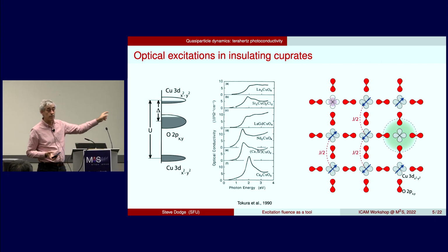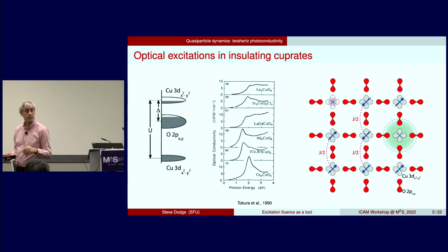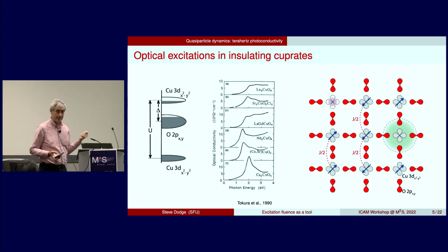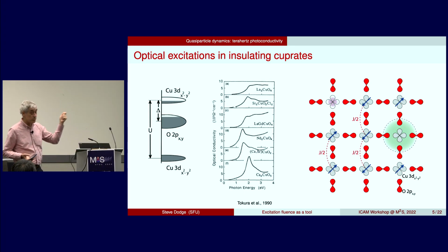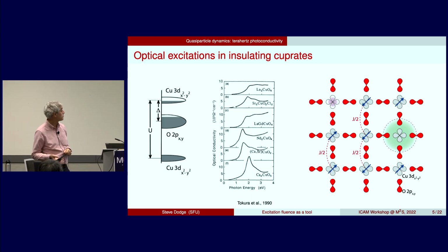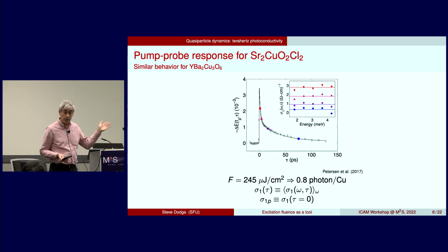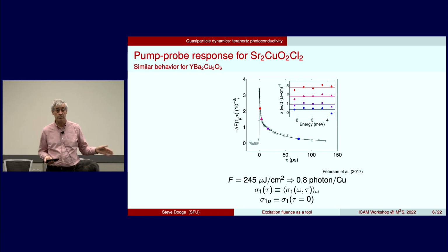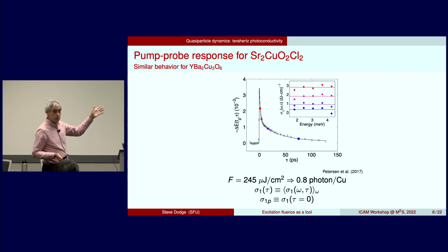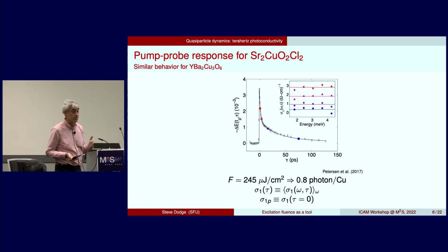But of course, as it does so, it leaves misaligned spins. So it's not immediately obvious that that is a free carrier, because there's an energy that it loses as it moves away from what I'll call the doublon, which I've represented here in pink. But when you photoexcite it and you probe with terahertz, it turns out that you can see a clear photoconductivity signal. Over our bandwidth, which is out to about 4 meV, these are basically flat. So if you extrapolate to zero, you're just looking at the DC conductivity as a function of time.